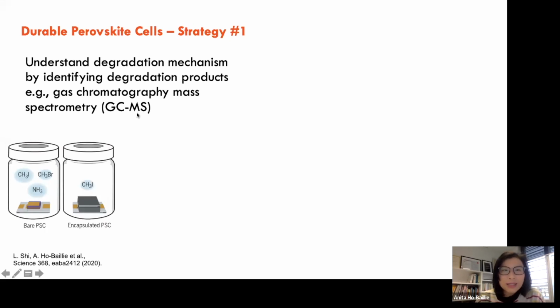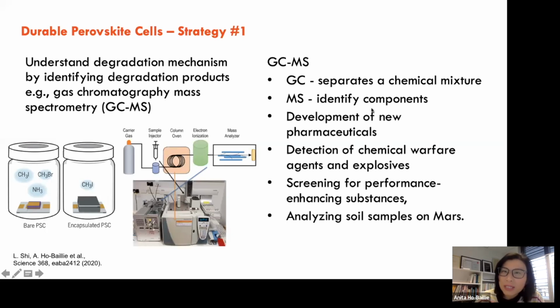We use a technique called gas chromatography mass spectrometry. And guess what? It's been used for detection of chemical warfare agents or explosives, screening of performance enhancing drugs, screening drug cheats, or even analyzing soil samples from Mars. Gas chromatography allows you to separate a chemical mixture, and mass spectrometry allows you to identify what the gas species are. So what we did is we took the perovskite solar cell, naked, just made on top of glass, and also perovskite cells that are encapsulated, meaning packaged and protected. And we stress them thermally, and we see what comes out.